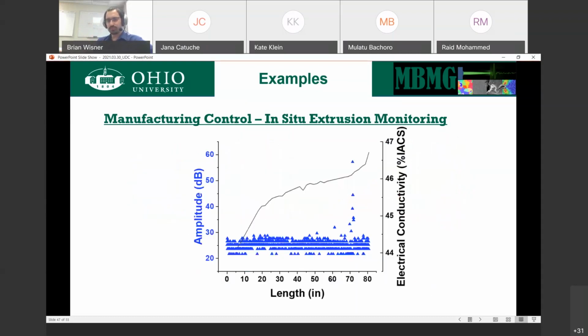But what we do know is that if we plot the electrical conductivity as a function of material length, and we plot the AE as a function of the material length, whatever caused these signals also caused a change and an improvement in the electrical conductivity. So this section here between 20 and 60 inches in length is a consistent process. Up to 20 inches in length is the initiation of the material, so that usually is going to get cut off. And this end point usually is the end of the material, which gets cut off. So something changed at the end that causes us to have better conductivity. If we can understand what that is, perhaps we can find a way to replicate it earlier, so we improve the electrical conductivity overall over this entire wire.